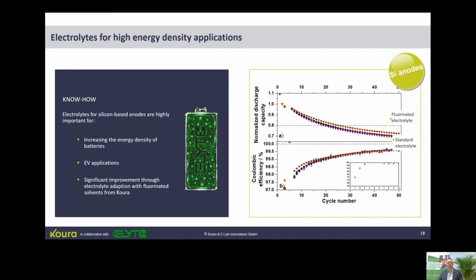The big volume expansion of silicon leads to ongoing consumption of lithium ions, and this is, of course, the reason for this fast cell fading or capacity fading. This is also something which we can improve by using adapted electrolytes. And in this example, we use fluorinated electrolytes from Koura, or compounds from Koura, which we introduce in the right way to existing electrolytes. And what you can easily see is that we can increase coulombic efficiency and also cycle life.